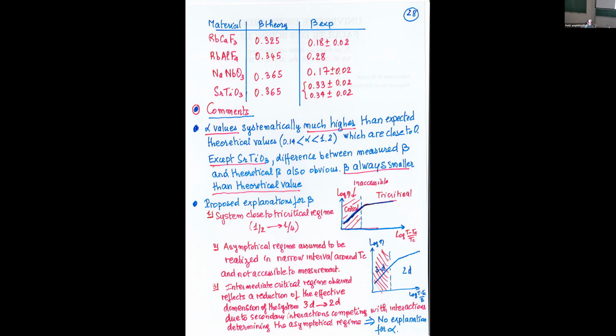we are not far from a tricritical regime. You know, the tricritical point is defined by the fact that the fourth degree coefficient becomes 0, and so you have to take into account the 6th degree coefficient. So if you minimize, then you find that your coefficient, let's say beta, varies with the power not 1/2 but 1/4. And so when you go near to this tricritical point, of course you go from 1/2 to 1/4, and so you have a smaller exponent.